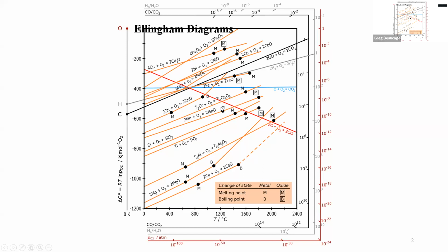So when you use a diagram like this, the thing you're trying to do, you're going to take the negative of the negative, which will give you a positive. And then your garbage can is going to be carbon to CO or carbon to CO2, right? And that's also a negative number. If that's a bigger negative number than your negative number for your oxidation, which you're going to run backwards, that means the net of those two is going to be negative. That means it's a go. That means you're reducing the iron oxide to make iron. So you're taking your ore and you turn it into steel. That's the thing you want to do at a steel mill.